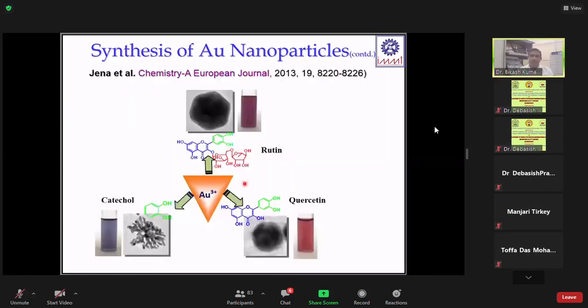In 2013 we also published our work in Chemistry European Journal. We took three different molecules: rutin, a biomolecule, quercetin, another biomolecule, and catechol. You can see the reducing functional group in all of them is the catechol. Just by changing this structure to the catechol, different shapes of nanoparticles formed. You can see some six-sided shaped nanoparticles forming, and some fractal structures and spherical particles. So this is about the beauty of green synthesis of nanoparticles.